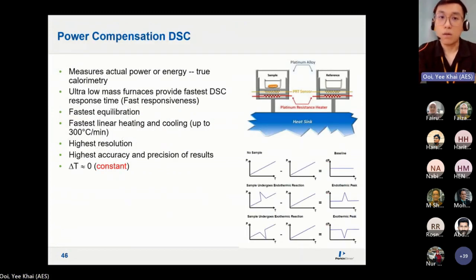So power compensation DSC measures actual power energy. We usually call it true calorimetry because there are no conversions, and because the furnace design is very, very small, you have the fastest responsiveness of the furnace. All this means you can do very fast heating, fast cooling, and the fastest temperature equilibrium. And due to the design, you can do linear heating and cooling. Remember I said for thermal instruments, regardless of what you are doing, it should always be under control. So this unit allows you to heat up your sample at 300 degrees C per minute and still be within control. It gives the highest resolution, accuracy and precision of results because there are no mathematical conversions.